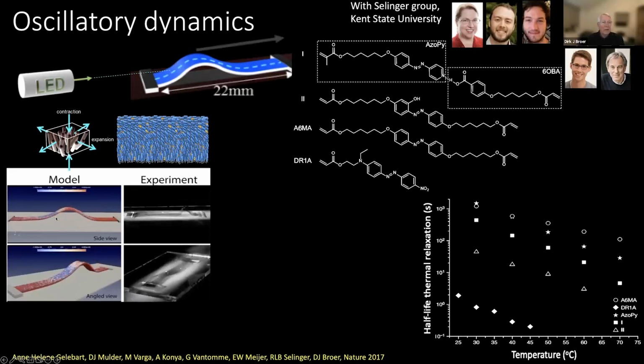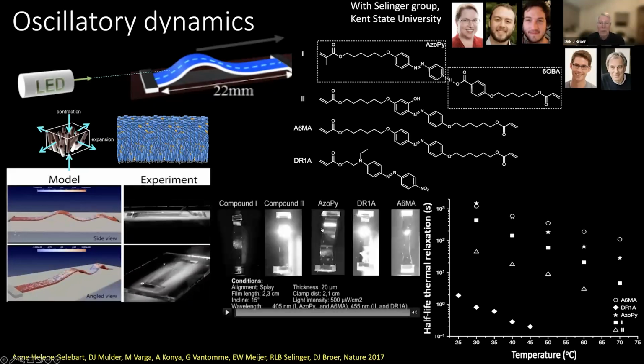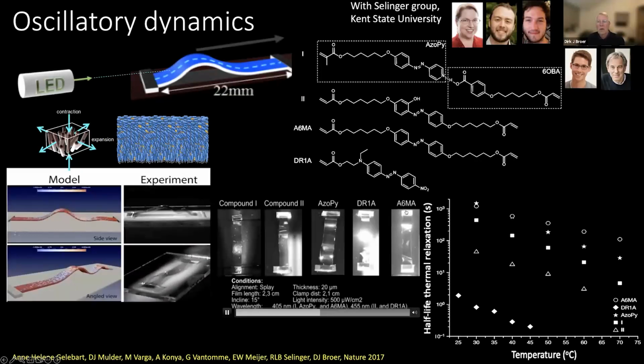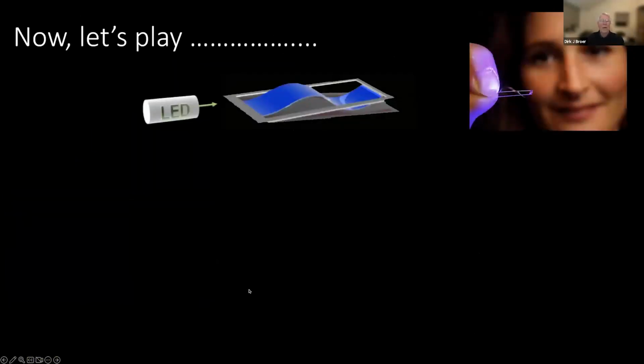So what you can basically create in that case is a wave in this structure. But in order to get this wave functioning, your motor molecules, in this case azo molecules, must relax fast enough from the cis state back to the trans state. And for that, we had to do some synthesis to create molecules, mainly using push-pull mechanisms in the system to get them converted from the cis to the trans state. And I have some examples here. Here you can see that slower working samples hardly show any wave formation, whereas the fastest relaxing materials show fast deformation.